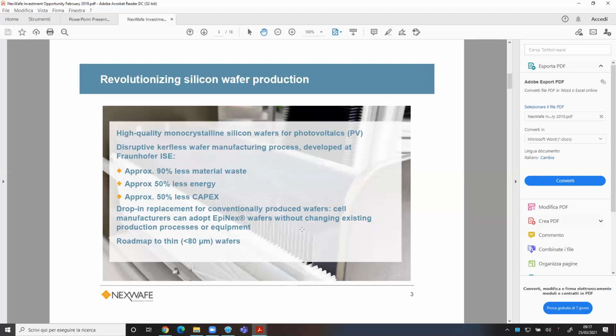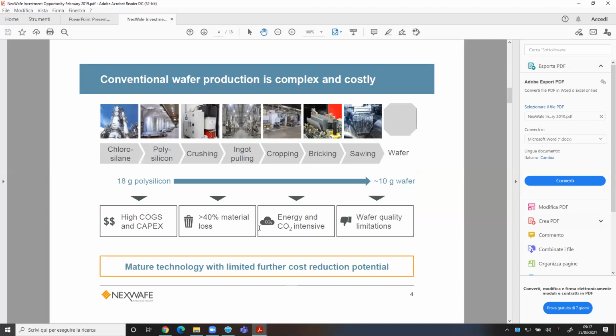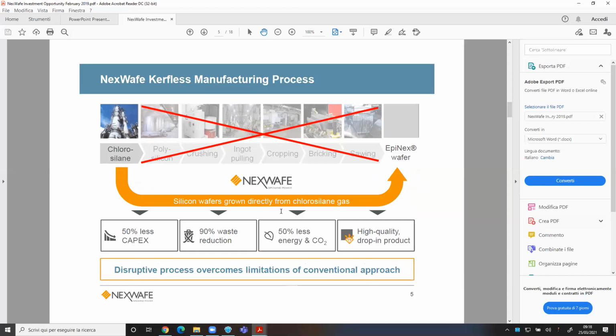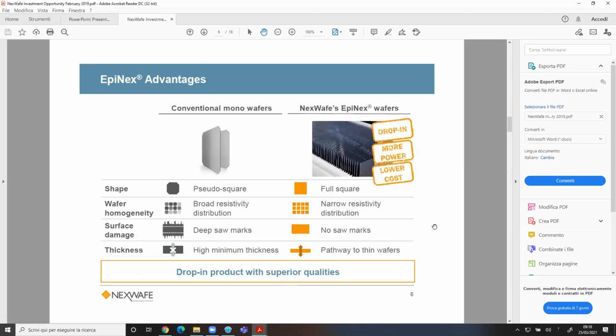So obviously there is much less waste. The process allows us to go from chlorosilane and polysilicon directly to the wafer with one single manufacturing process, instead of crushing, ingot pulling, cropping, bricking, and sawing. This obviously reduces the capex of the manufacturing by around 50%, with 90% waste reduction, 50% less energy, and a very high quality wafer.